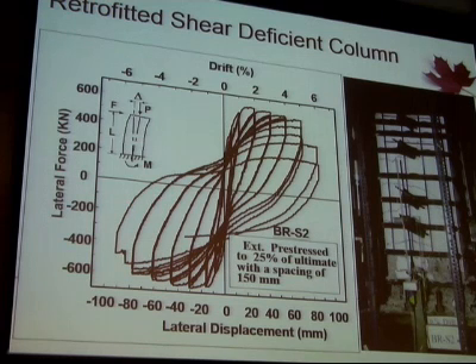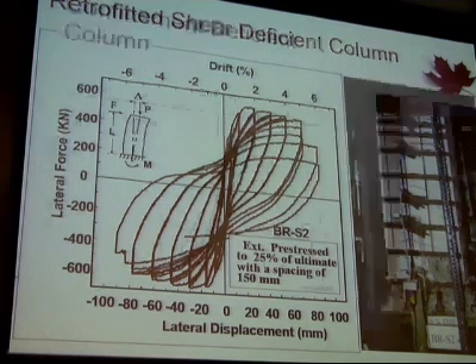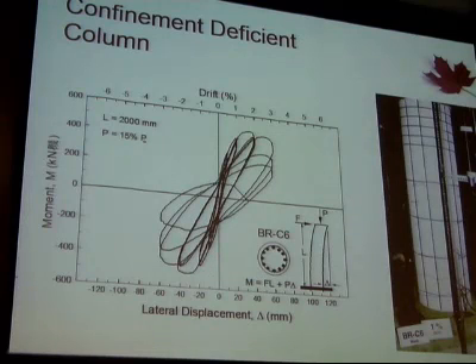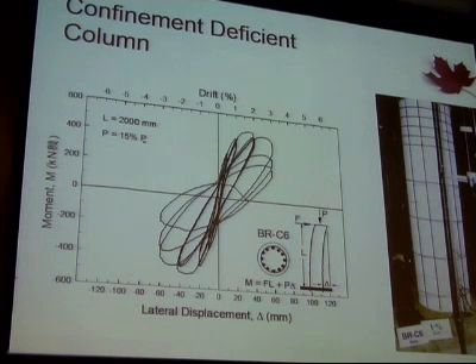But obviously, subsequently, as the cracks start increasing, then reinforcing or the pre-stressing still kicks in as additional transverse reinforcement. So it does provide two functions. It improves the V sub C term, the concrete resistance to diagonal tension. It also adds additional steel against shear. And this is a comparison now for confinement effectiveness of this combined active and passive lateral pressure.